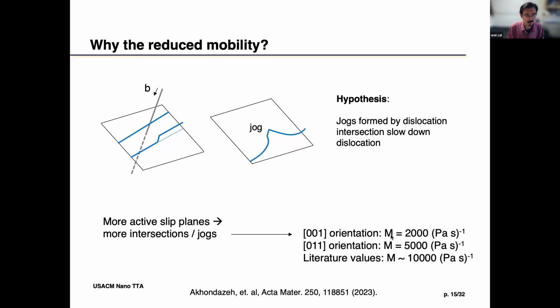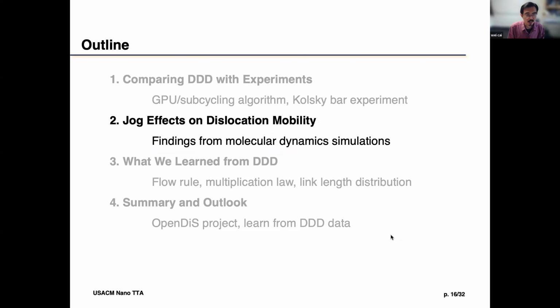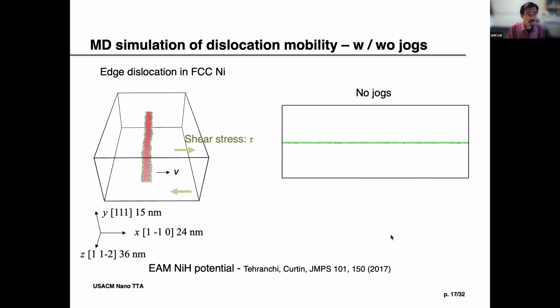So the paper was published with that conjecture. But then we said, okay, maybe we should test it. Okay, let's see whether that's the case. So these are some MD simulations we did to test that hypothesis. We start out with this MD simulation of an edge dislocation. This one has no jogs. If you look from the side, the dislocation is exactly on its plane. So there's no jogs.